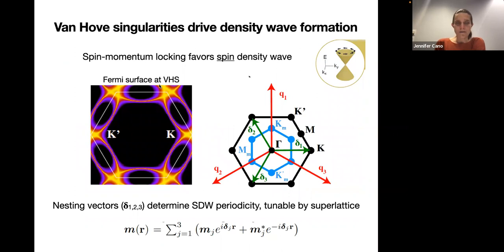So these Van Hove singularities can also increase the effective strength of the Coulomb interaction. And since they're located near the K and K prime points, so not at the gamma point, they're going to drive some kind of density wave. And what happens for our topological surface is that it drives a spin density wave instead of a charge density wave. The reason is because this is a little sketch of the TI Dirac cone. As you move around on the Dirac cone, as you move around in momentum, spin also moves. So spin and momentum are locked. That's the unique property of Dirac cones on the surface of topological insulators.